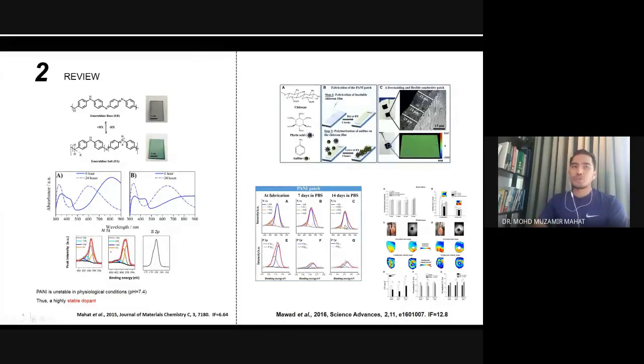So in here, we want to see and measure whether this dopant has actually improved the system. We have tried many acids before, and all are unstable. So in here, phytic acid was suspected and expected as well to work as a cross-linker with the polymer, which is the polyaniline, and the chitosan.